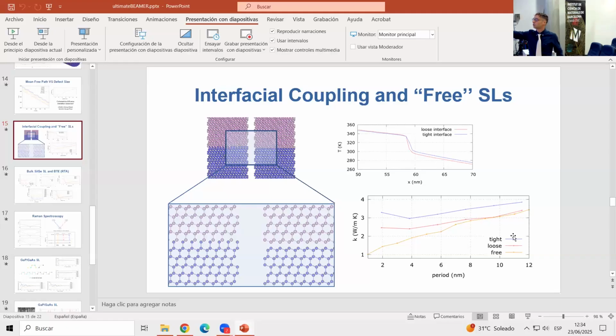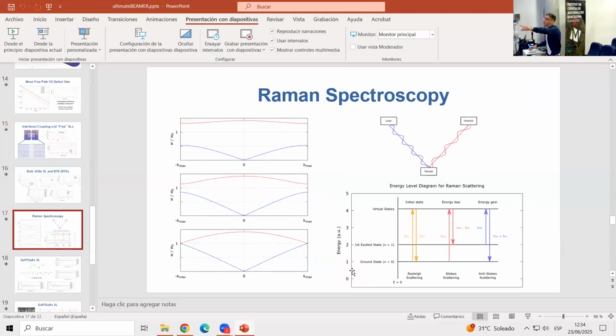even though, strictly theoretically speaking, it is okay not to find any coherence, because when you break the periodicity, even if it's a very, very subtle periodicity breaking, you do not have any k-vector at all. You still have phonon modes, but since there is no periodicity, you don't have any k-vector. So in principle, you can have an infinitely broad range of very low frequency modes. They are all just collapsing to zero frequency oscillations or very high oscillations. But the modification of the spectrum, here I plotted the phonon spectra in the continuous limit. Here, if you could resolve for a finite material, you would see it's not a continuous line, just points. Okay, these are specific phonon frequencies. This structure is a direct and straightforward result of periodicity. Theoretically speaking, pure periodicity. Maybe you can do something treating the periodicity breaking as a perturbation. That is beyond the scope of this thesis, by far.